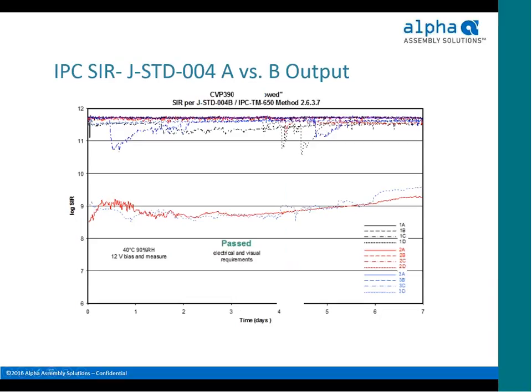With J standard 004B, it's a much more robust set of data. Now we can actually graph the SIR performance over time for the entirety of the 7 day test. So this gives us not only just static measurements at different points in time in the test endurance cycle, but it also gives us trends. For example, if the resistance was still falling over time or had increased greatly at one point in time, we could see that and we can make decisions based on that with respect to the reliability of the material. In this case here, to be passing, all of the data has to be above the 8 line on that log SIR on the vertical axis, which represents 100 megaohms. So in this case, we can see that we passed, two outliers that were low, but the rest of them at very high values.